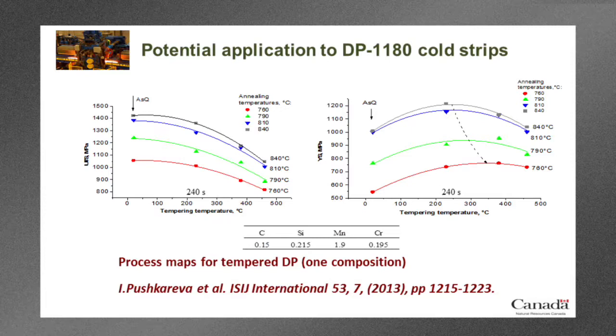It could be due to some kind of incomplete segregation of carbon to dislocations during the quench, and this is completed by the tempering step, so you get a residual, an extra hardening effect. But we really don't know, to be honest with you. There are a few explanations that are possible. All I want you to understand is that it's actually quite complex, the behavior that you get.